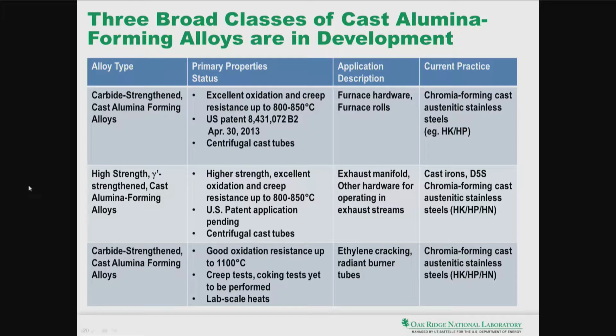So we have three broad classes of alloys that we are working on, and these are targeted at specific property requirements in those classes of components that we are targeting them for. I've just briefly summarized this in this table here. We have carbide-strengthened cast alumina-forming alloys that are primarily topped off at about 800 to 850 C in terms of temperature of applications. These are covered by US patents, shown here, issued US patents. And the form we think that these will be used in is centrifugal cast tubes. Of course, these are furnace hardware, furnace rolls, and traditionally they are dominated by the Chromia-forming cast austenitic stainless steels.